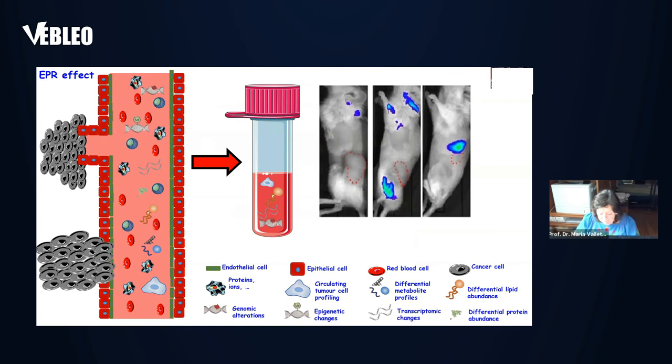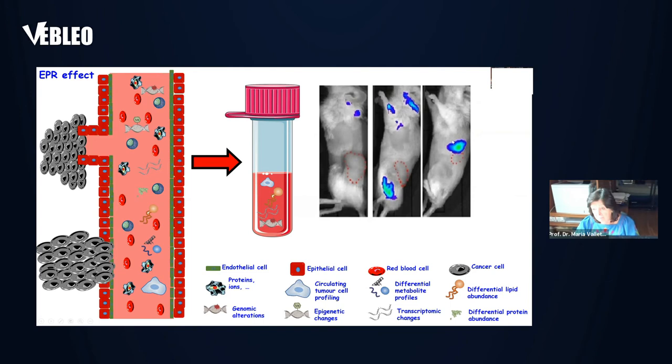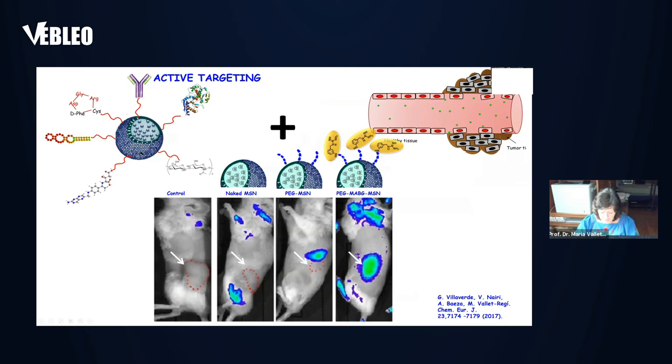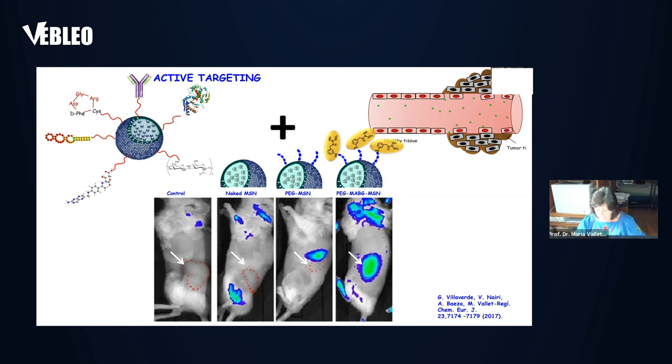The way to achieve their arrival to the target is by EPR effect. But it is not enough in many cases. It is then necessary to add a particular specificity that makes the nanoparticle reach the target through active targeting. The surface area of mesoporous silica is used to attach ligands that could drive nanoparticles towards the tumor. For example, folate, a cyclic peptide, or hyaluronic acid are attached to mesoporous silica nanoparticles for targeting. Together with passive targeting mechanisms represented by EPR effect, mesoporous silica nanoparticles can be targeted to the tumor. In this case, you can see that it works very well with active and EPR effect together.